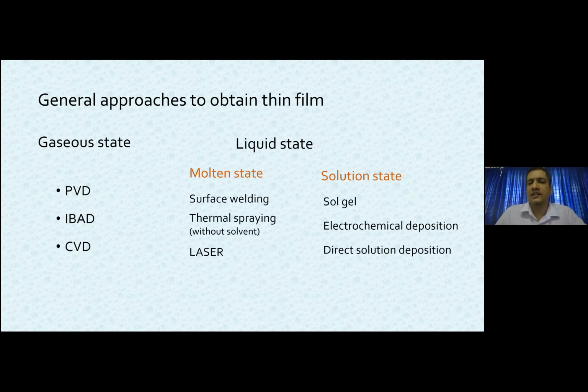When you come to liquid state, you can directly melt and do the coating, surface welding, for example, or thermal spraying, or you can do something called laser assisted coating at high temperature. All these involve slightly higher temperature. This requires the substrate to withstand that high temperature. So that's the one confinement when you work on the gaseous state and molten state, that the substrate should be robust enough to withstand this high stringent environment. To circumvent this problem, other approaches involve solution state, wherein you go for sol-gel techniques or electrochemical deposition, or you can go for a direct solution deposition.